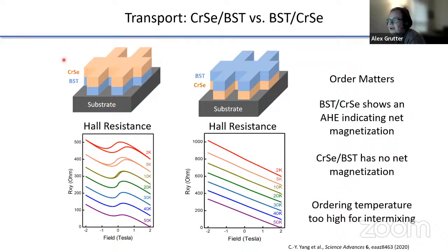So when Chaoyao grows these films in different orders, chromium selenide on top of bismuth antimony telluride gives you a really nice anomalous Hall effect. And on the other hand, bismuth antimony telluride on top of chromium selenide gives you a straight line, no anomalous Hall effect at all. And so this tells us two things. First of all, obviously the order of the growth matters a lot. And it's probably not going to be a situation where we have an intermixing induced signal.